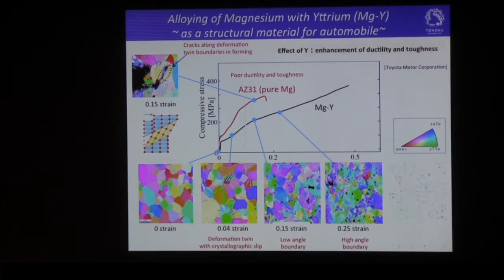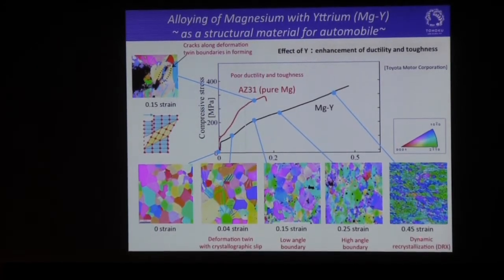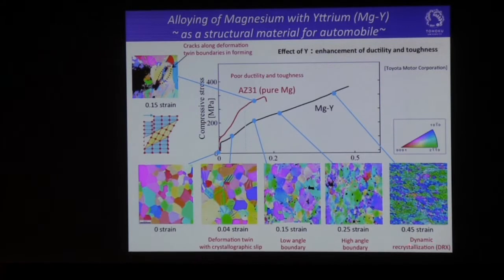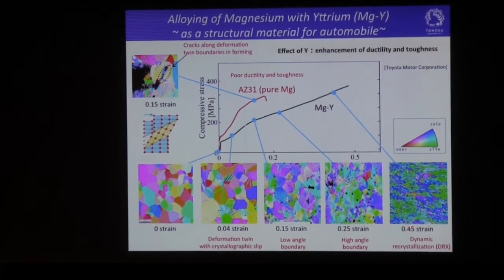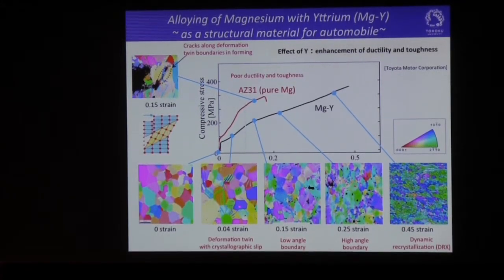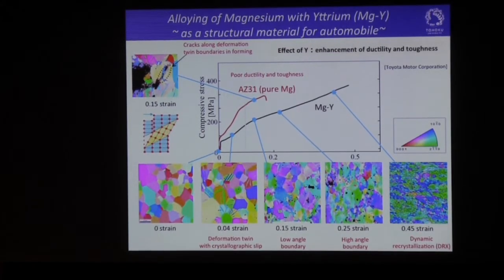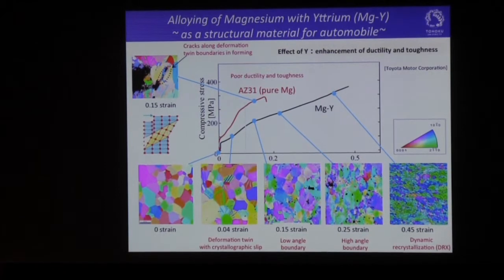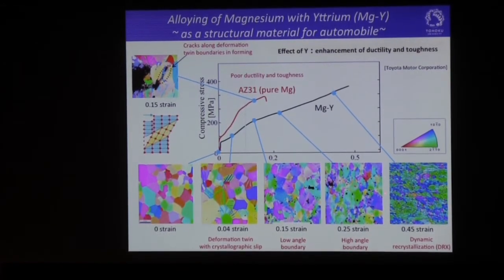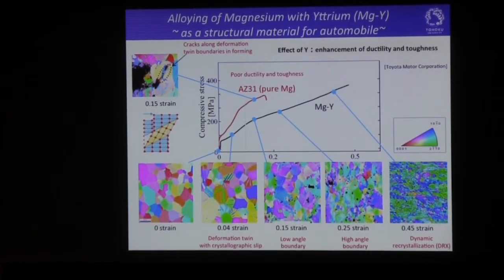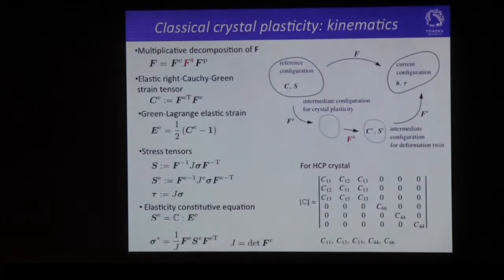After the final stage of deformation, we could have this kind of dynamic recrystallization, which involves grain refinement. These two kinds of deformation mechanism, that is deformation twinning and also dynamic recrystallization, probably make the material more ductile and tough. Okay, so I'd like to simulate this kind of complex microscale deformation in order to characterize the corresponding macroscopic material behavior.